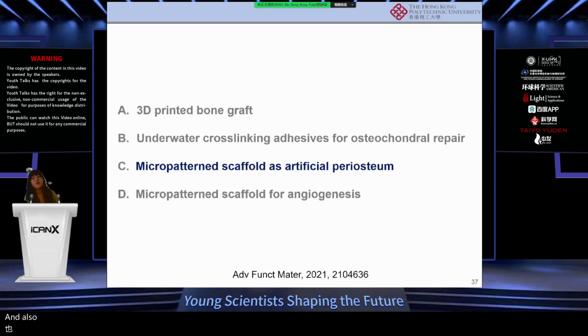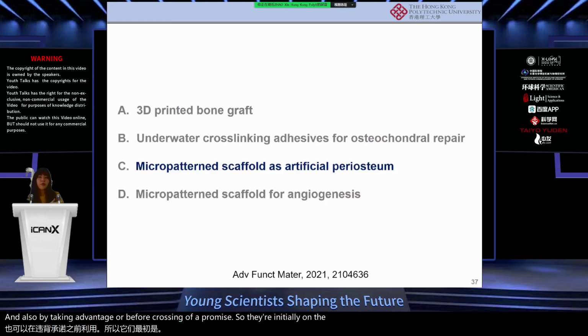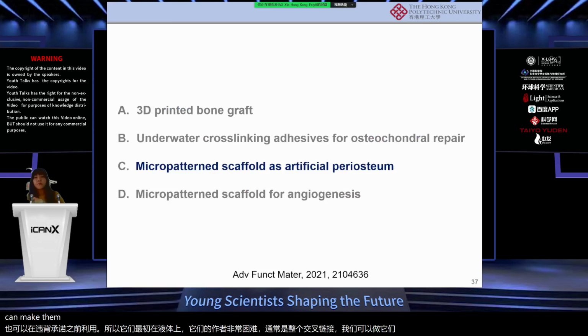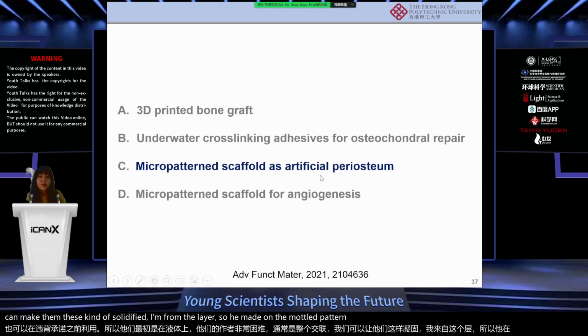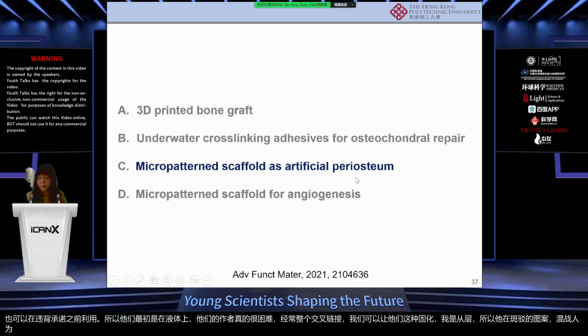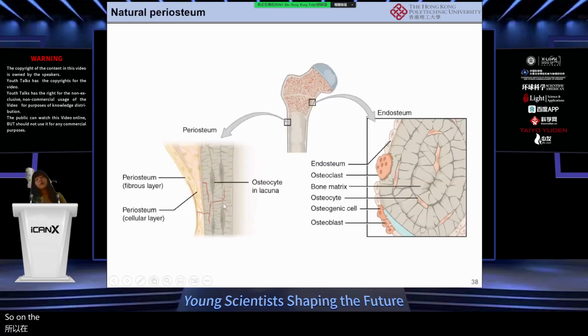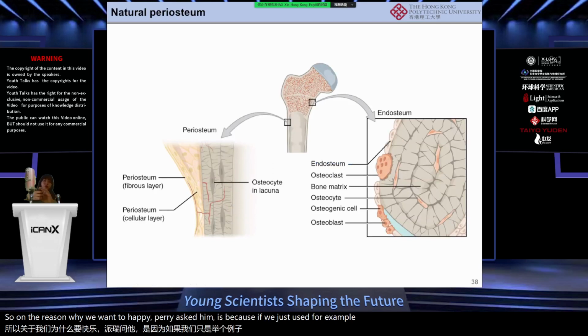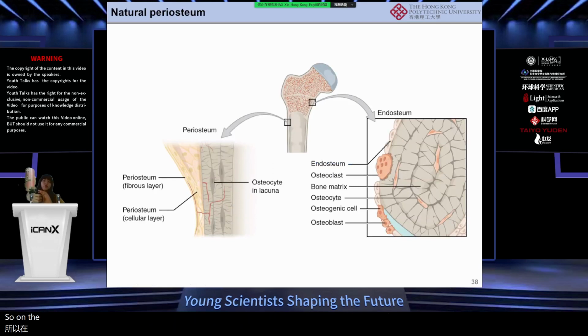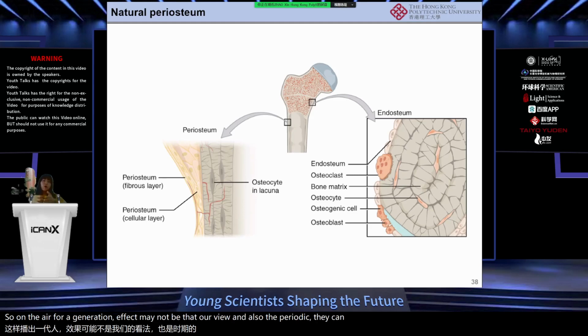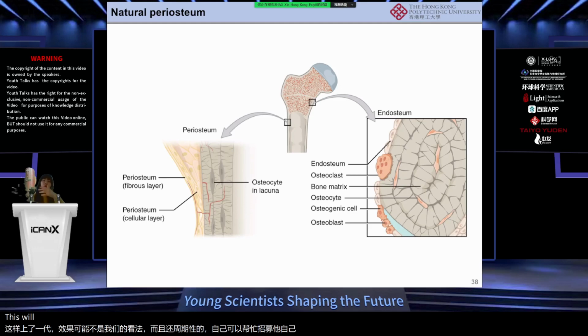And also by taking advantage of the photocrosslinkable polymers, they're initially liquid, and then after solidification or photocrosslinking, we can make them this kind of solidified polymer layer. So we made them the micro pattern scaffold as artificial periosteum. The reason why we want to have the periosteum is because if you just use, for example, the bone implant, the bone regeneration effect may not be that ideal. And also the periosteum can help to recruit the blood cells. These will also help the bone regeneration.